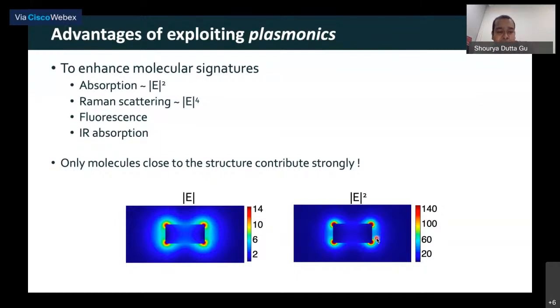So what this allows us to do is enhance the signal from the same volume or concentration of molecules. Another thing you will notice is that if I have molecules here, only then will I get a strong signal. If I put the same molecule here, I'll get a very low signal. So I'm also reducing the volume or the concentration of molecules over which I'm getting the signal from. So these are two common ways that you can use plasmonics for sensing, which we'll come to later.